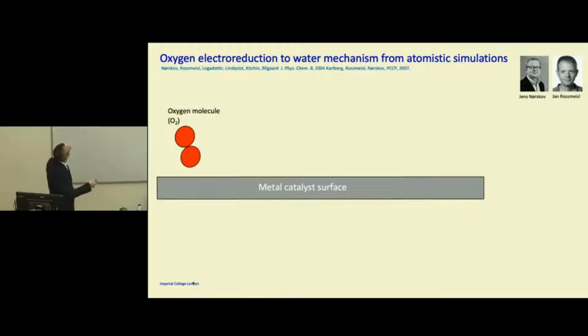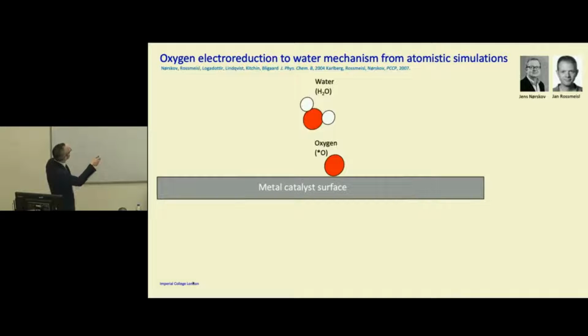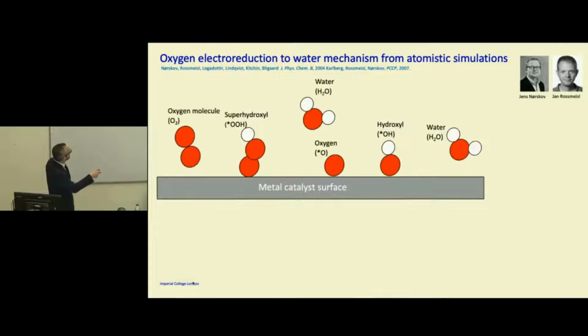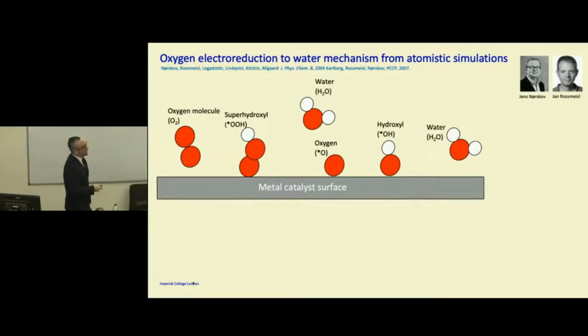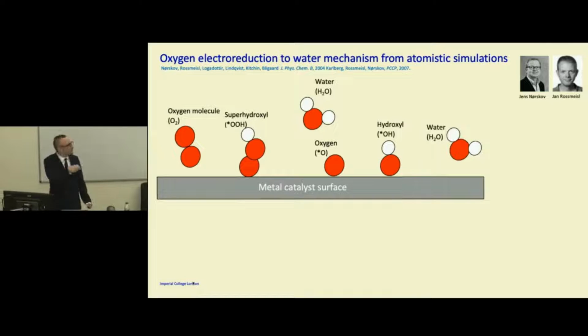So essentially, you have an oxygen molecule, then you protonate it, you add a hydrogen there. So these two are oxygen atoms. Protonate further, you make one more oxygen molecule, water molecule, and then protonate further, make hydroxyl, and then you make water. So this is the overall pathway. So ideally, you want to react with all these different species, but you don't want to react too strongly with them, otherwise you'll never go the complete cycle. So you need to bind an intermediate amount to it.